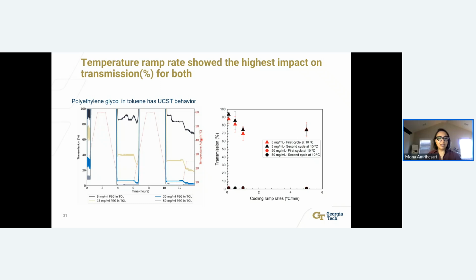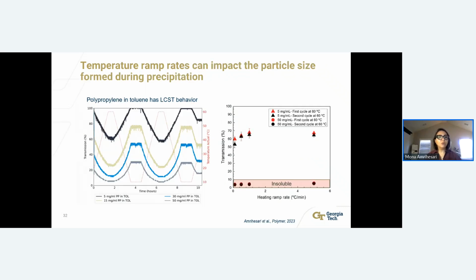Here on the right, you will see the plot of the transmissivity versus the cooling ramp rate as these polymers start precipitating at lower temperature. What we observe is that we get to a plateau value at 1 degree C per minute, but before that, the transmissivity is higher when we have a lower cooling ramp rate, meaning that the size of the particle is not big enough, or the drop does not fully come down to a lower transmissivity value. But looking at whether it's statistically significant, there is not a significant difference between different cooling ramp rates. And then we looked at the polypropylene in toluene, which has the LCST behavior.